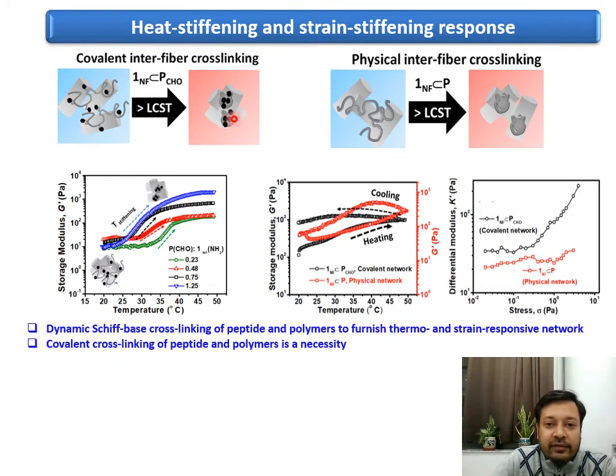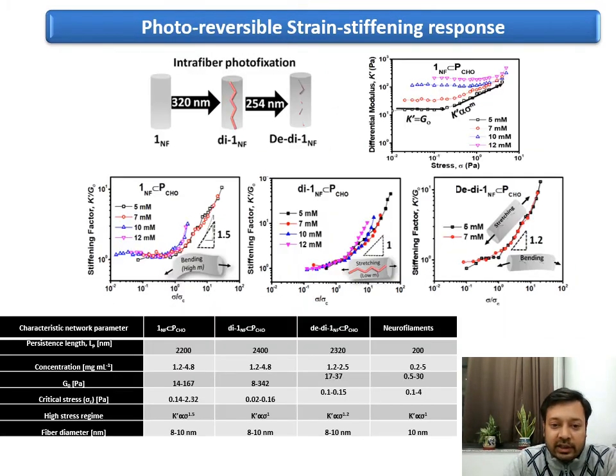Now we looked into the heat stiffening behavior in the covalently cross-linked medium, and in the case of physical cross-linking, where the polymer did not have any aldehyde functionality. We did see that we can have a very nice heat stiffening because of the polymer chain collapse. In the case of covalent cross-linking, we did see that it can have a very nice permanent memory of the stiffening response. However, the covalent network formation is very important, because that only shows a very nice nonlinear response, whereas in the case of a physical network, you don't see such a nonlinear response.